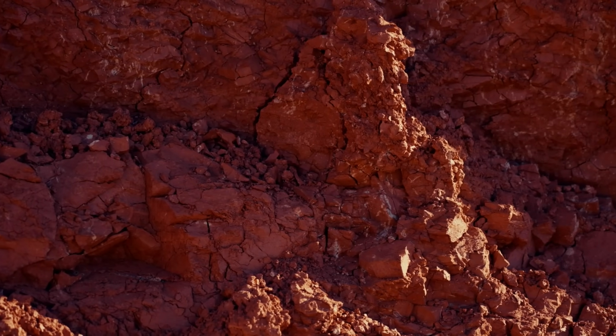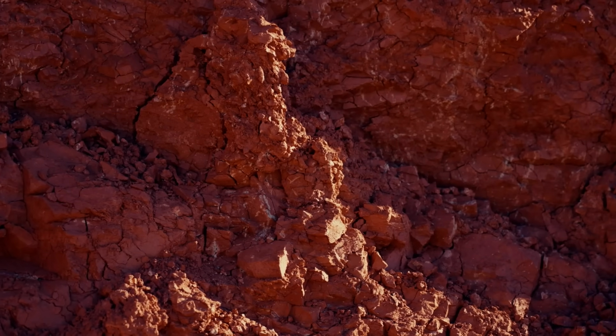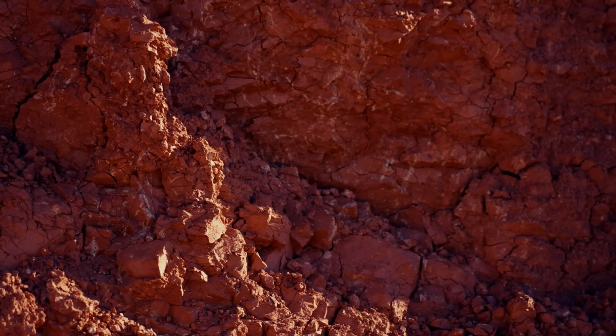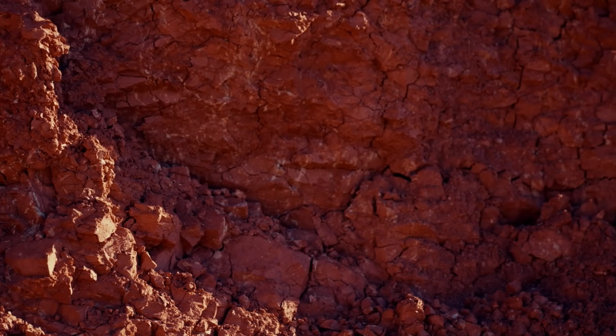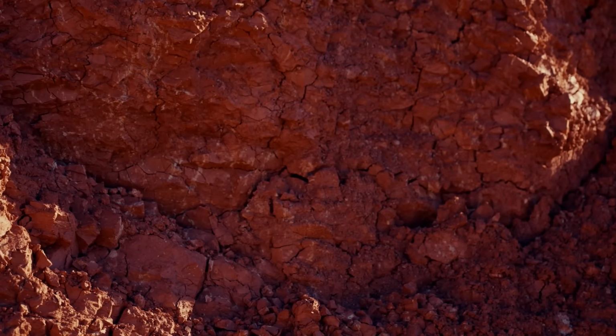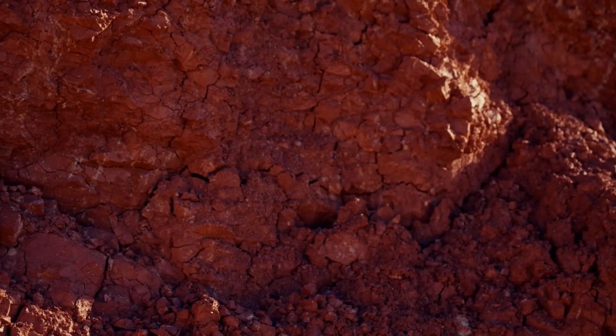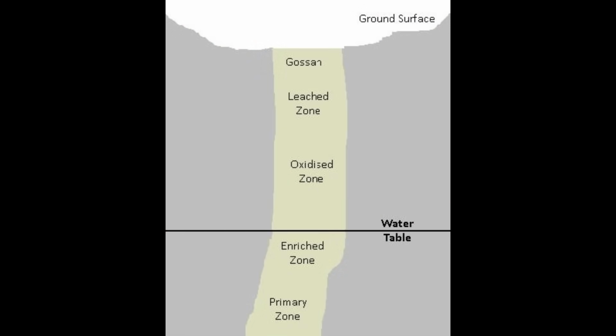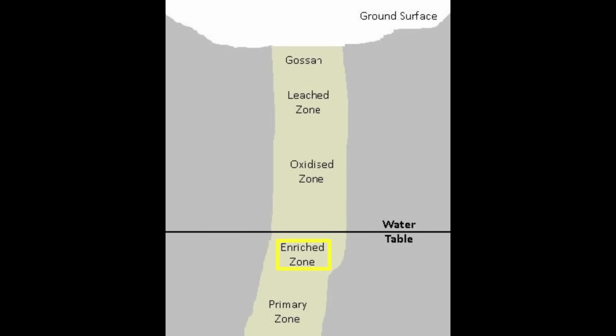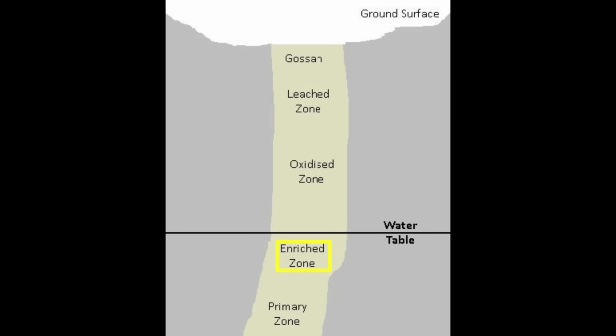They're not chasing the colour, they're reading the history. They're asking what used to be here, what has been removed, what conditions existed to form sulfides in the first place, and where is the boundary between oxidized and unoxidized material? Because that boundary, the transition zone between fresh sulfides below and iron oxides above, is often where things get very interesting. Gold can accumulate there. Fluids slow down, the chemistry changes, it's a natural trap within the system. If you can find that zone, you're no longer guessing, you're targeting.